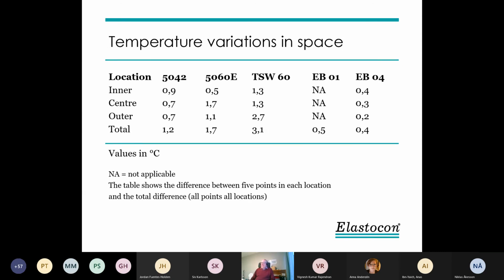And there were the differences, as you can see, if you take the total: 1.2 degrees, 1.7, 3.1. The oven with 3.1 had a window in the door, and behind that window, 50 millimeters behind the window, it was much cooler than in the rest of the oven. Our own ovens are in the range of, say, 0.5, 0.4 degrees.